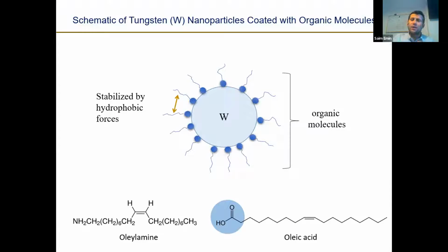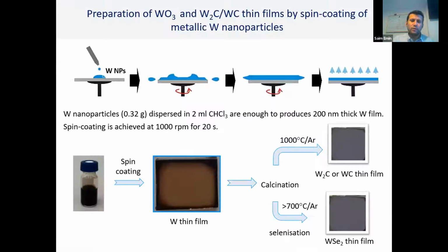What we have is metallic nanoparticles covered with some molecules, and they are very well dispersed in organic solvents, not in water. And we can spin coat them. Basically, they are very stable. Once synthesized, they can be stable for years. I have samples from 2018. They're still stable in my drawer, dissolved in the solvent chloroform.